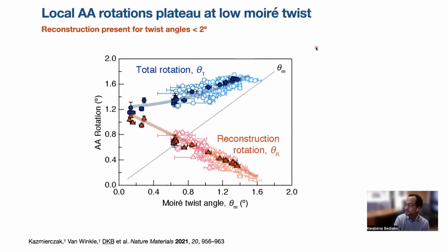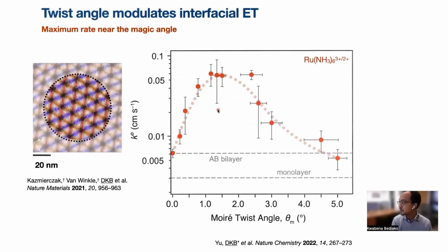The importance of this is that when we do these experiments, our SECCM electrochemical experiments, measuring these kinetics as a function of twist, remember our pipette is maybe 100 nanometers to 300 nanometers in size. And so what we're doing is an ensemble measurement over many Moiré superlattice sites. And so that's what this measurement is.